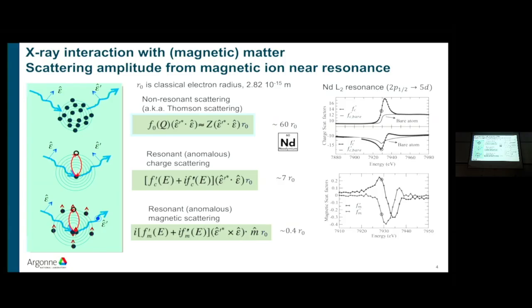This is the scattering amplitude, and what you measure, these are complex quantities because the imaginary part of these things are responsible for absorption, and the real part are the typical dispersions that you get when you are at a resonance. So a Kramers-Kronig transform of the imaginary part. When you look at these effects, you don't see any magnetic field here. It's all electric field. So it's all related to an electric dipole interaction. And these two resonance scattering phenomena are a second order process where n is this intermediate state where you have this virtual electron that senses the valence electrons, and then it goes back,